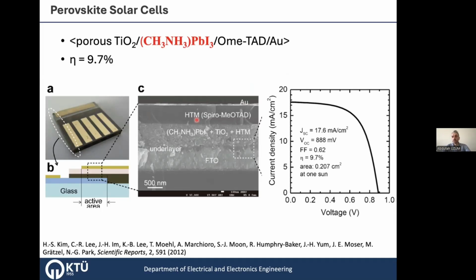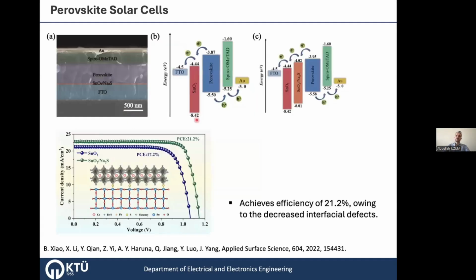At that time, it was a single deposition process, and after that, a double deposition process was introduced, and the efficiency of perovskite rose gradually. And remember the first graph, the efficiency graph, that the efficiency progress of perovskite is very fast, very rapid. This is a good thing for research, but still not state of the art. And in the coming years, this is a study from 2022, approaches have been going on with different materials, different interfaces, different hole and electron transfer materials. This is an example of tin oxide with some additives for the electron transfer layer, and they show an efficiency of 21.2%.